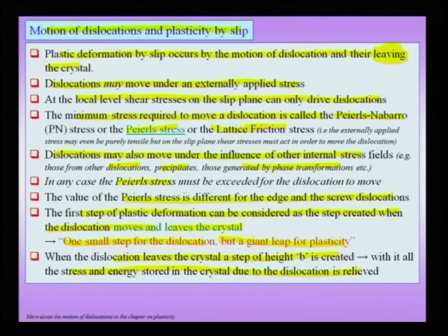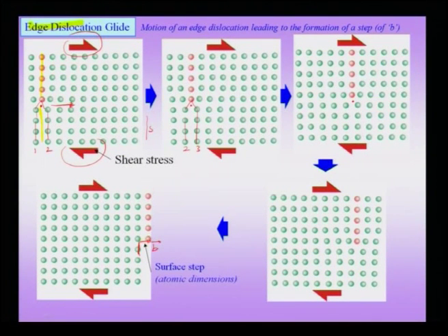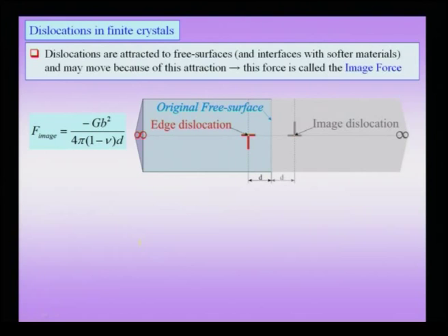the dislocation expresses itself as a vector, what you might call a vector of strength b, on the surface of the crystal. If you look at dislocations in infinite crystals, then they have a certain stress field, and if I am only talking about a single isolated dislocation in an infinite crystal, such a dislocation feels no forces. Of course, when you apply external forces, that force may translate into shear stresses at the slip plane level and it may feel the shear stresses, but in the absence of external loading, such a dislocation would feel no forces. But suppose I consider a dislocation in a semi-infinite crystal.